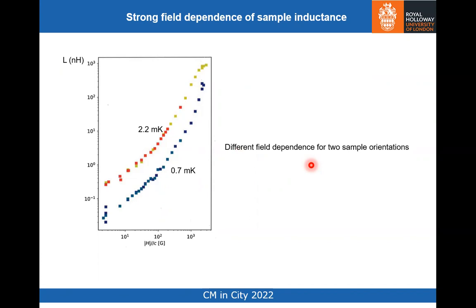It could have a really boring explanation in terms of inhomogeneities in a sample with a spin triplet order parameter that's oriented in different ways throughout the sample. That modifies the path, and these different orientations have different critical fields, which means that the pathway for a supercurrent through the sample becomes more and more tenuous, and the more tenuous the pathway, the higher the effective kinetic inductance is going to be via this geometrical contribution to the kinetic inductance. So that could be going on.